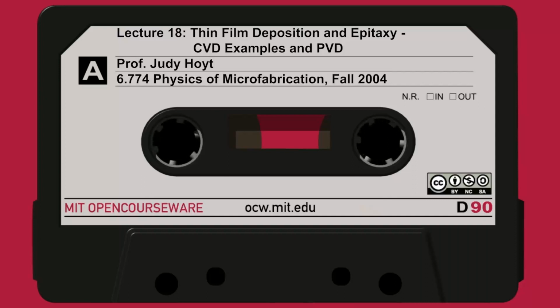I'm not going to talk about it in great detail in the course. Diffusion through polycrystalline silicon is quite different from what we've talked about, diffusion in single crystal silicon, because in polysilicon the dopants can diffuse along the grain boundaries. Look at this example, labeled B, called columnar grains. A lot of dopants, like arsenic, diffuse very rapidly down grain boundaries.